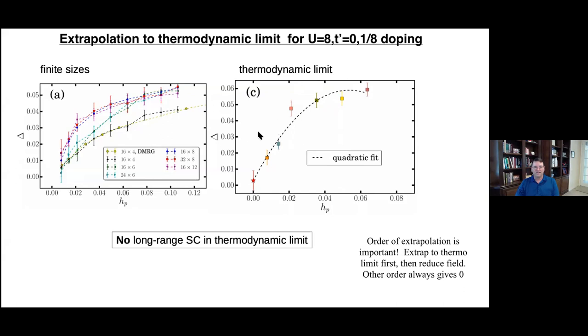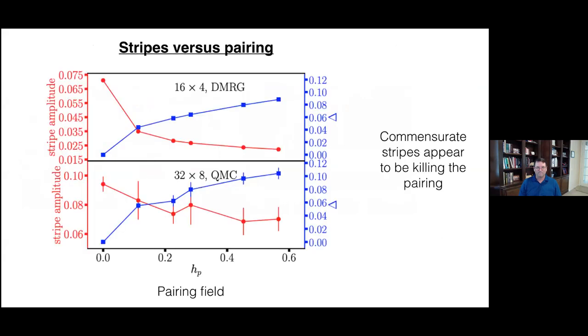And this technique is quite reliable, say if we do it on just the magnetization at half filling, we already know what goes on. Okay, so the conclusion is that there's no long range superconductivity in the thermodynamic limit at this particular point. And why is that? Well, if you look versus this pairing field and look at the strength of the stripes, the stripe amplitude is shown in red, and then you look at the strength of the pairing, you're seeing they're competing with each other. One goes down and the other one goes up. Okay, so it appears that these commensurate stripes are killing the pairing. And these stripes are also filled stripes, so that's the other thing that makes this particularly bad.